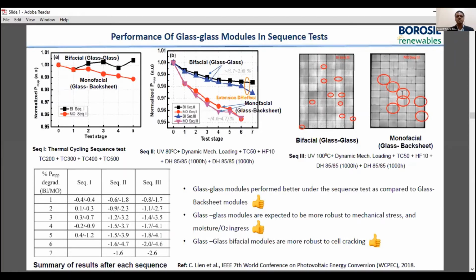What they observed is that the power loss is more in the case of the glass to backsheet module as compared to the glass module. All the top curves that you see, the bifacial glass modules in black or blue, have lesser degradation of power over the period of time. Even the thermal imaging shows a clear picture that the bifacial glass modules are more robust. They are still largely intact after these sequence tests. So it also proves that glass modules perform better under sequence tests as compared to glass backsheet modules. They are expected to better withstand these mechanical stresses and also moisture or oxygen ingress. Hence, they are expected to perform better in the field.